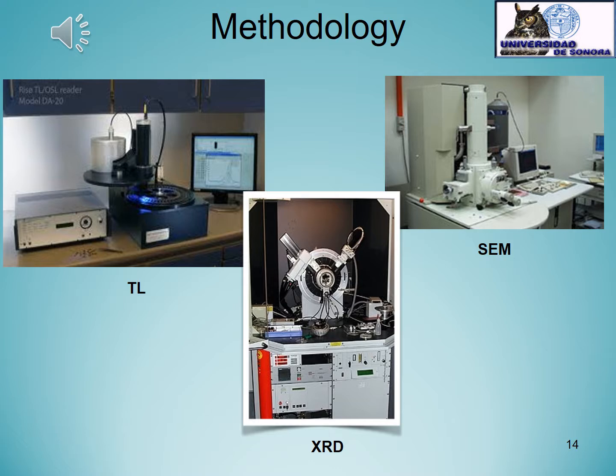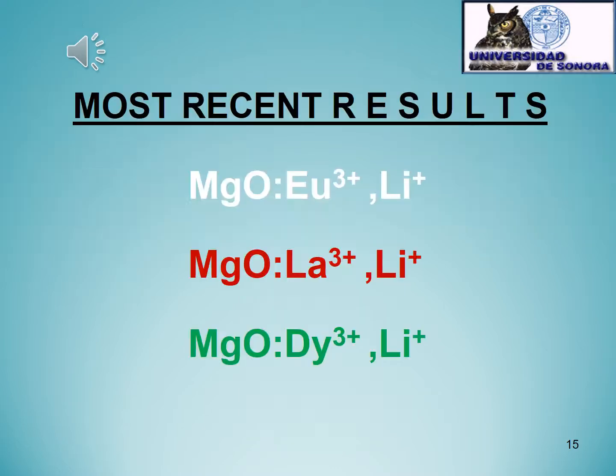For measuring TL, we use the commercial equipment RISO TL OSL reader model DA20. This equipment is built with a beta radiation source of strontium 90, and in the case of X-ray diffraction and scanning electron microscopy, we use the equipment from our department. We use this equipment in general for characterizing the most recent materials synthesized by SCS.